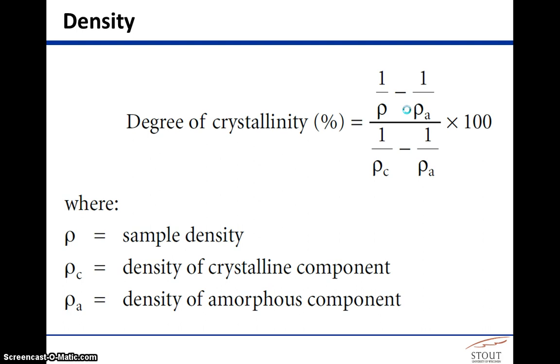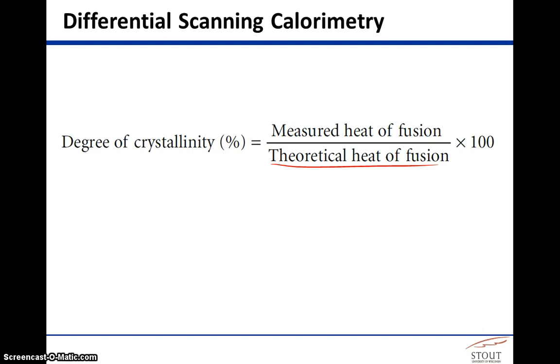Then, because the densities of amorphous and crystalline components of polymers are known, you can use tabulated data. Plug in your experimental density along with the known amorphous and crystalline densities, solve the equation, multiply by 100%, and you get the percent crystallinity. Ideally, if this is a critical measurement, you do both the density measurement and the DSC, and hopefully the two techniques agree — and usually they do.